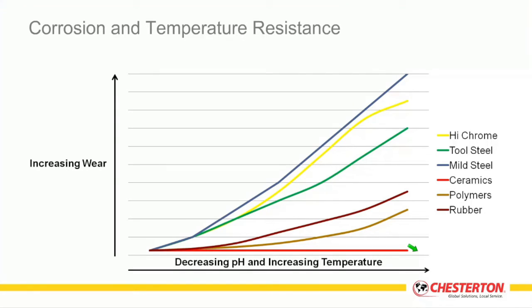So in this situation, ceramics, which are relatively inert to a wide range of chemical compounds, offer fairly consistent wear resistance over decreasing pHs, which would be your acidic range, and increasing temperatures. Conversely, your mild steels tend to perform worse in this type of application. So you want to be looking more at your ceramic-based materials under this type of situation, or you could look at polymers or rubbers depending upon the elastomeric system you're choosing. Is it a urethane-based compound, or is it a vulcanized rubber-based compound? Or from a polymer standpoint, what is the functionality or molecular weight of the polymers being used to provide you better temperature and chemical resistance? So those are 3 factors, impact, velocity, and chemical and temperature characteristics, that come into play in your material selection process.